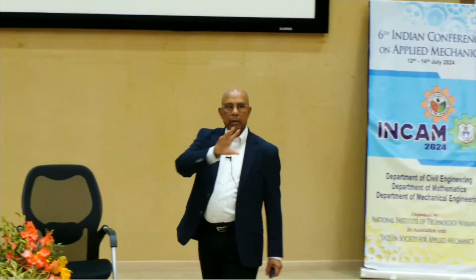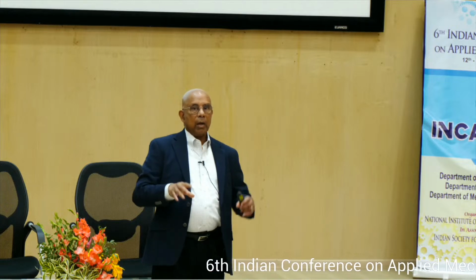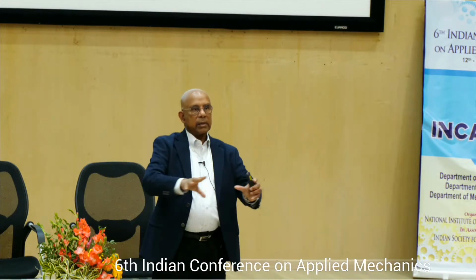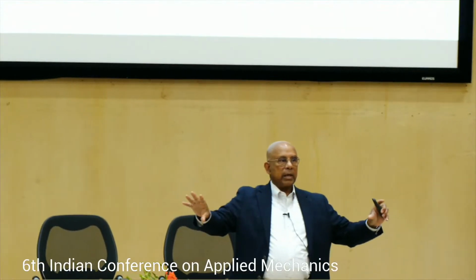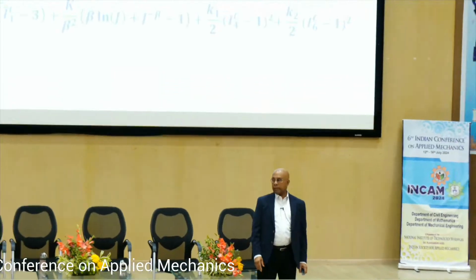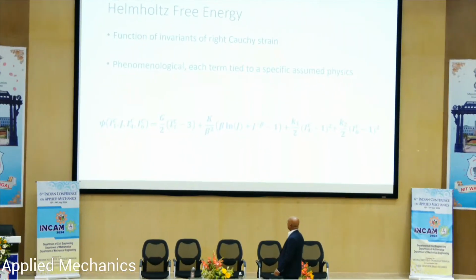So you have 4 terms in the free energy function. Psi equals the first term, the shear modulus term, which is shape change, not volume change. Thermodynamically they sometimes call it isochoric. The second term is volume change, the bulk term. The third term is fiber stretching under compression and tension. The fourth term is fiber stretching under shear. So the function has the failure of the matrix and the failure of the fiber appearing explicitly in the 3-dimensional constitutive equation. Okay, good.